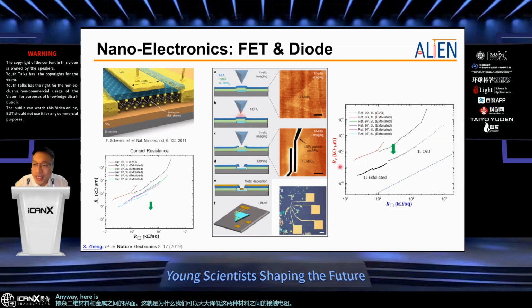Anyway, here are the results. Contact resistance versus sheet resistance of the materials. So basically, you have the sheet resistance representing the carrier concentration of the materials, and this is how good the contact is. These two lines represent the contact made by EBL, and these three sections of line represent the contact made by scanning probe lithography. As you can see, we have reduced the contact resistance using the same materials with similar carrier concentration. So this is a good reduction of the contact resistance.